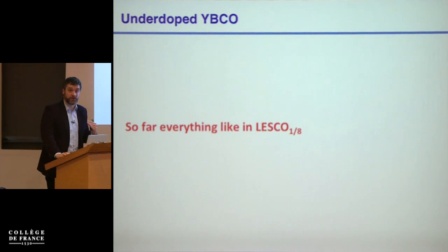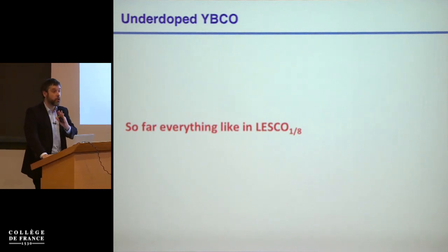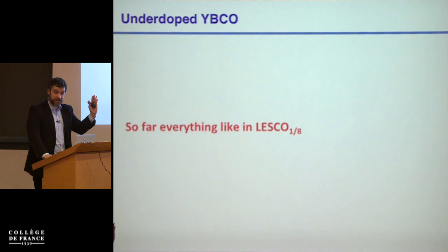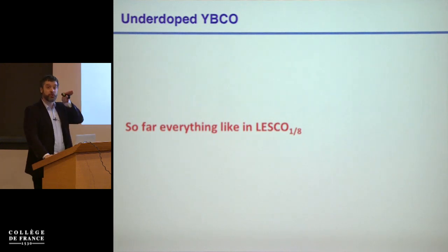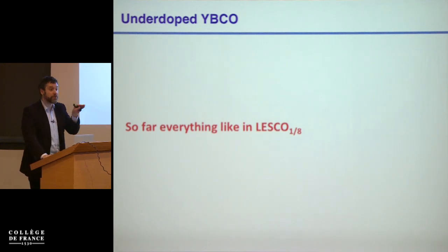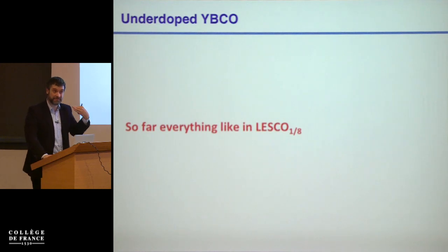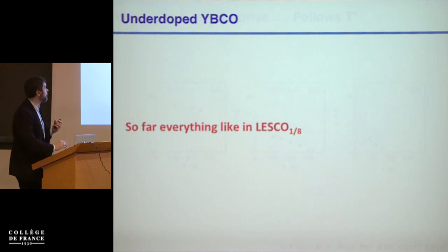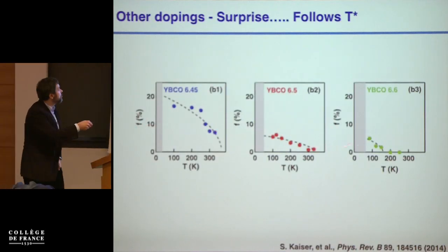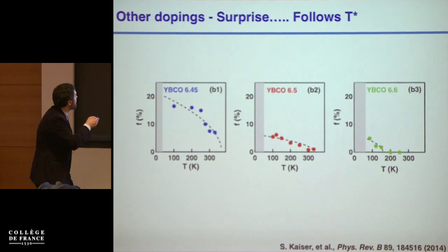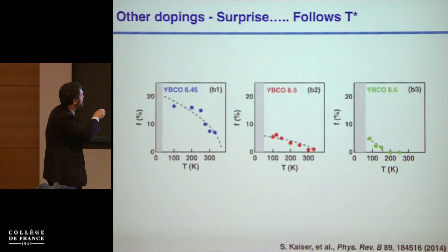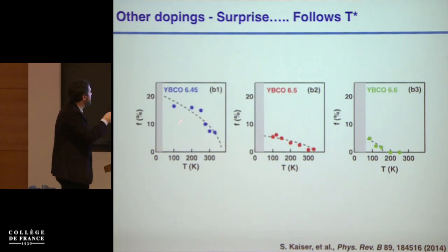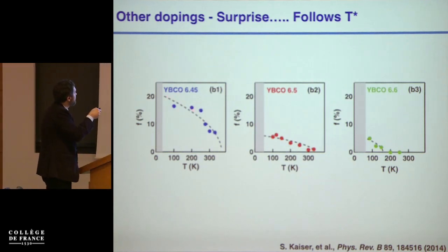What's really surprising though in YBCO is that if you now go toward underdoped regions where the charge order temperature goes down, you would expect the light-induced plasma edge to be observable only to lower temperatures. And this is not what you observe. What you observe when you go to lower dopings is a stronger effect. This is some fit that is related to the size of the effect. And you observe the effect all the way to, say, room temperature or so.